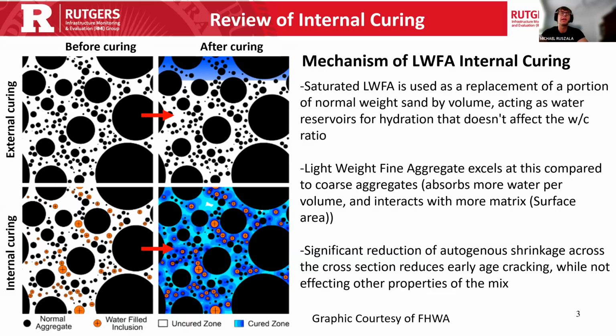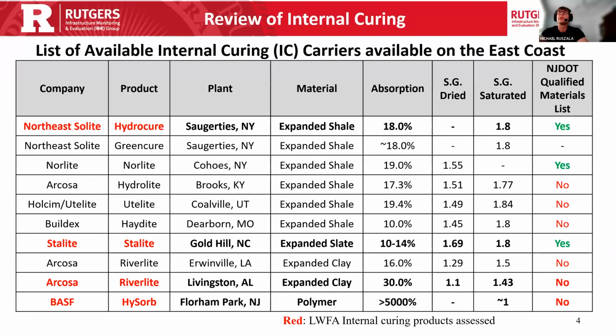One way to mitigate this is by using internal curing, where this curing compound or curing carrier is dispersed throughout the cross section. It applies more consistent water distribution to the matrix, and it really does significantly reduce autogenous shrinkage, which we'll see in the upcoming testing portion. And yeah, this has been seen to significantly reduce cracking. So we'll get into what internal curing carriers are available on the East Coast, so that's specifically of interest to the New Jersey market.